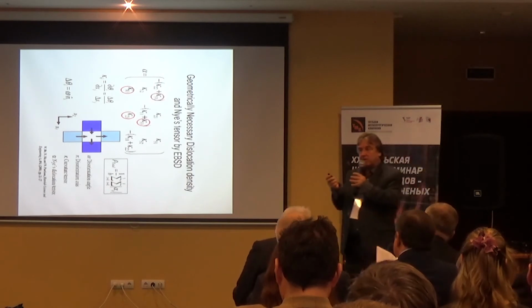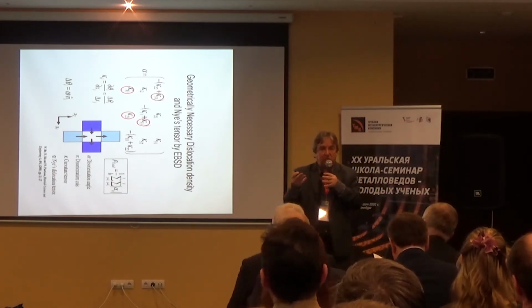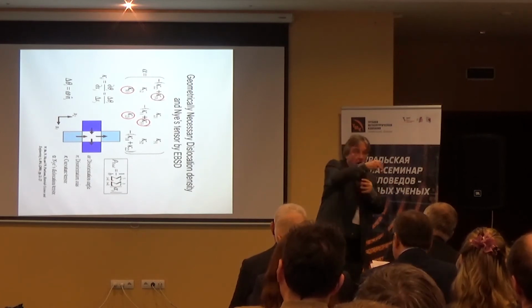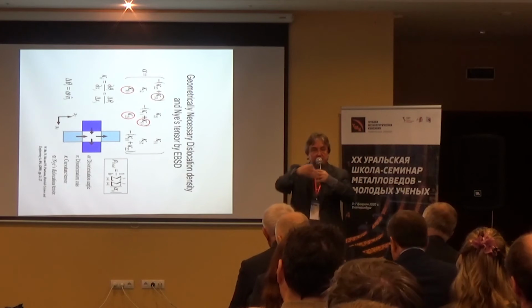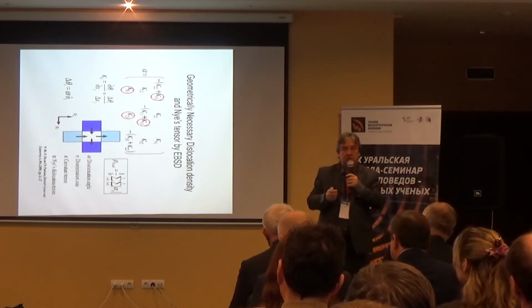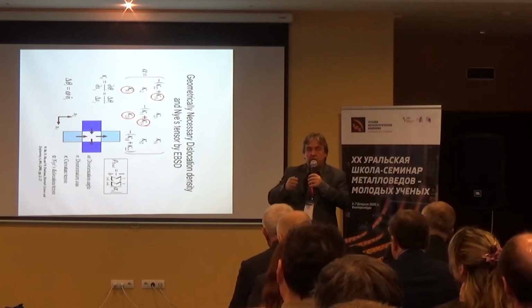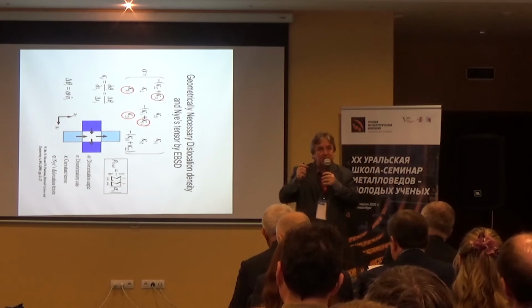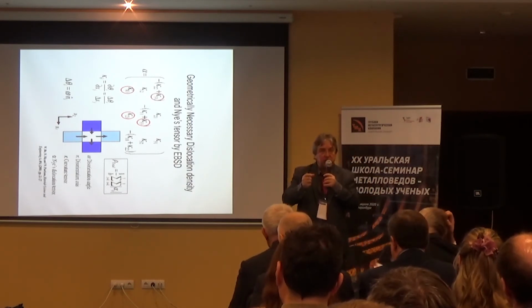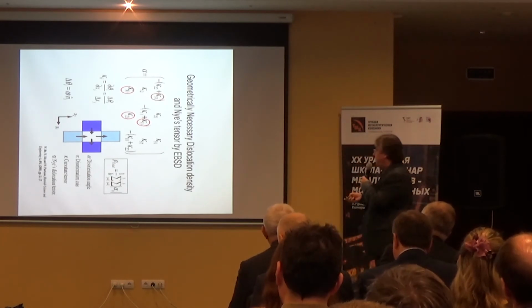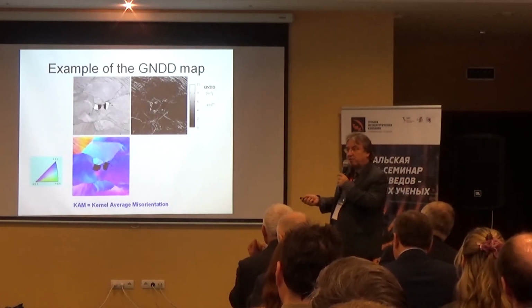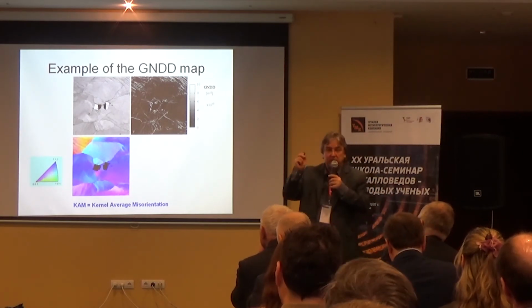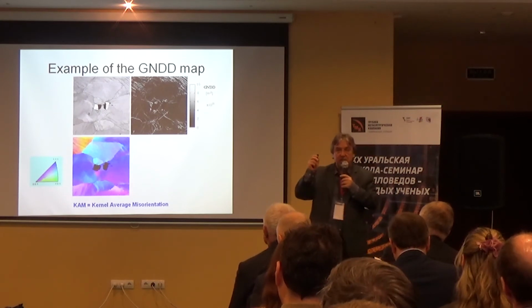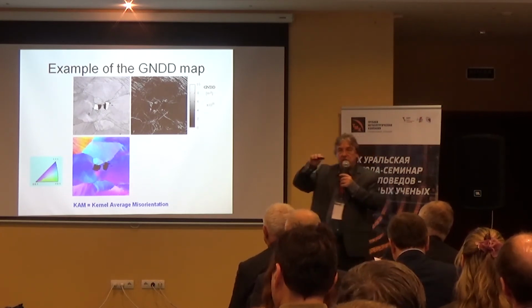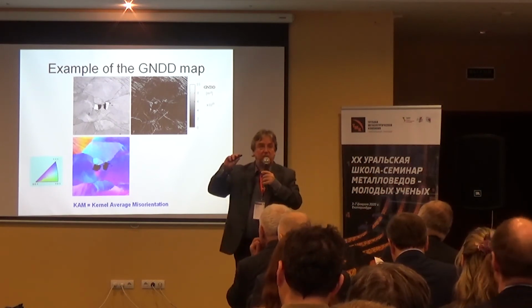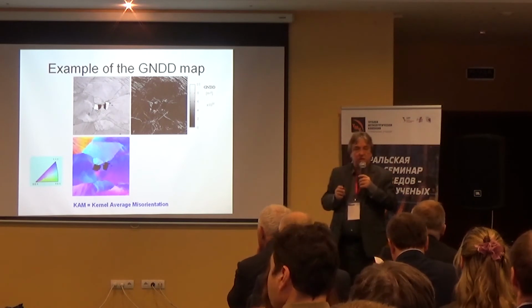This is a statistical quantity. You cannot say of one specific dislocation, you are a geometrically necessary dislocation. No, it's a statistical property of a group of dislocations. And this property is responsible for accommodating crystal rotation. And this crystal rotation, this misorientation, we can measure. Therefore, we can derive from EBSD data the density of geometrically necessary dislocations. Not the total density of dislocations, because the total density will be the geometrically necessary dislocations plus the statistically stored dislocations. But this information we cannot obtain by EBSD.